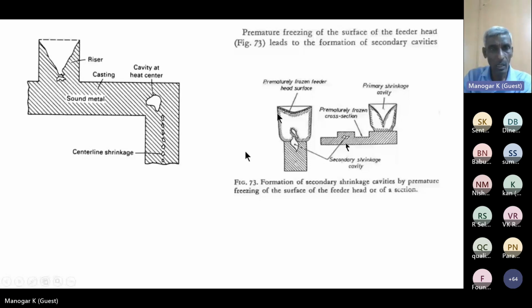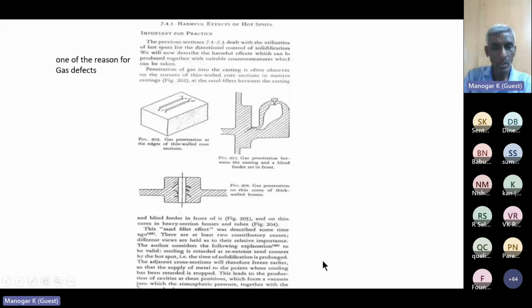And sometimes we assume this is a pinhole porosity, but it is a centerline shrinkage case. And in some of the castings, due to sharp cores and the flank being very close to the riser, a gas problem is created that should be taken care of and should not be mistaken for the defects. And always avoid sharp corners, sharp edges in the pattern, core, or in between the riser and flank section.